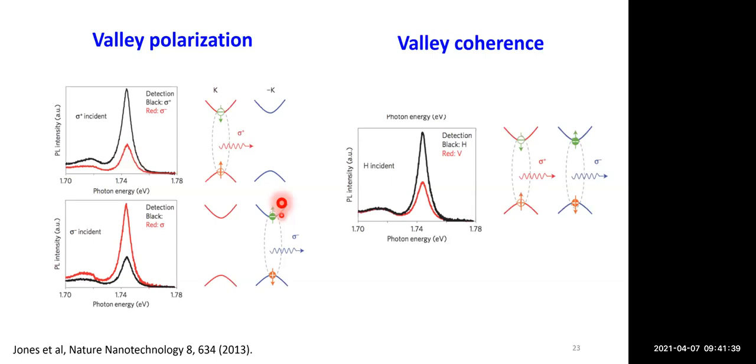Again, the creation and the detection of the valley coherence is another important effect of these valley optical selection rules. If you have a coherent superposition of the left and the right circularly polarized photon, which means a linearly polarized photon, you can transfer the optical coherence of the light into this excitonic valley coherence. Linearly polarized photoluminescence from a neutral exciton has also been observed. This is particularly for monolayer tungsten diselenide, and the polarization angle of the exciton always coincides with the angle of your linearly polarized excitation laser.